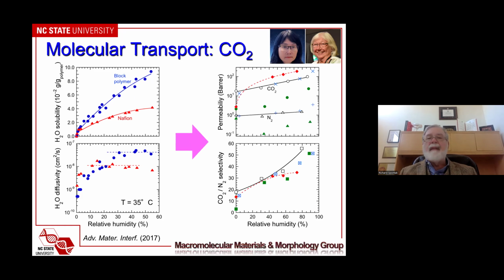If we look at the permeability of CO2 from both single gas and mixed gas measurements, we see that it is very, very well behaved as a function of humidity and definitely on par with what you would have for Nafion. But it's the selectivity that makes a big difference because it continues to increase as relative humidity increases, whereas for Nafion it levels out. Just to put this in perspective, Nafion consists of amphiphilic channels, just like the block polymer, but they're much smaller, typically on the order of about 2 to 5 nanometers, whereas for the block polymer, they're on the order of about 20 to 25 nanometers.